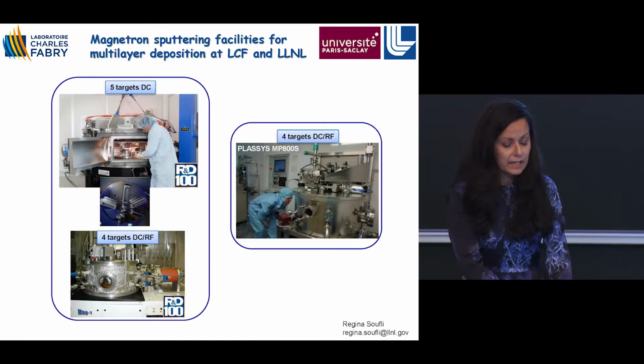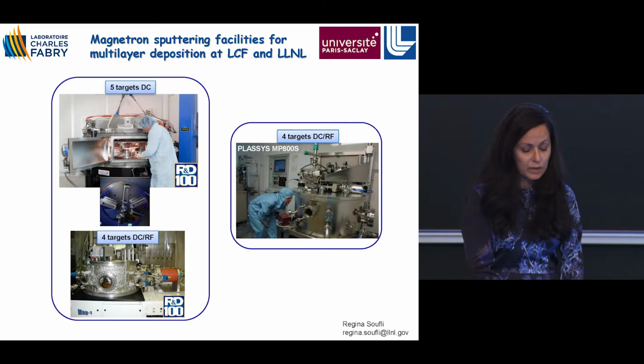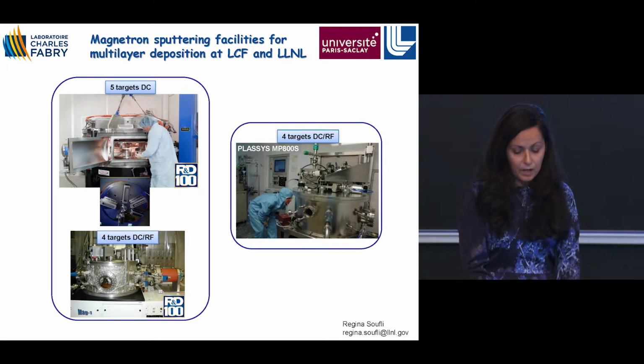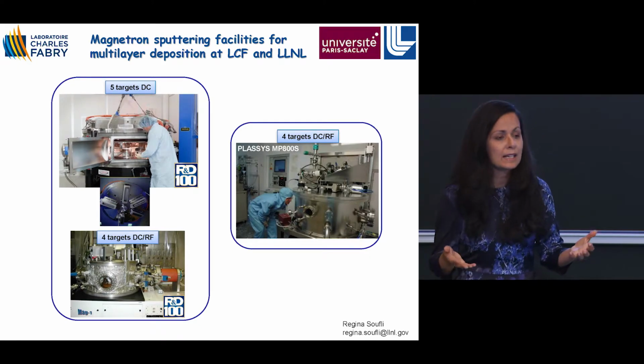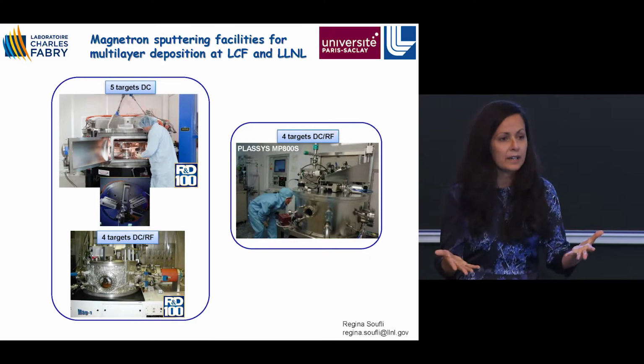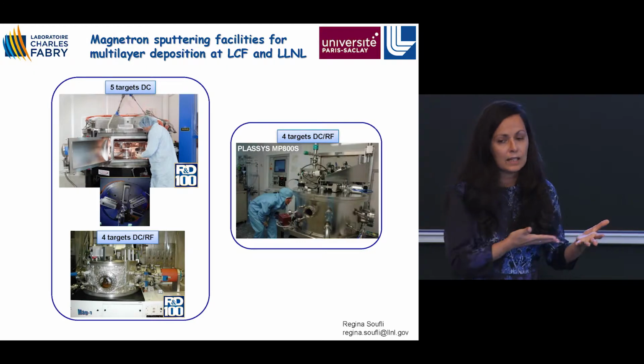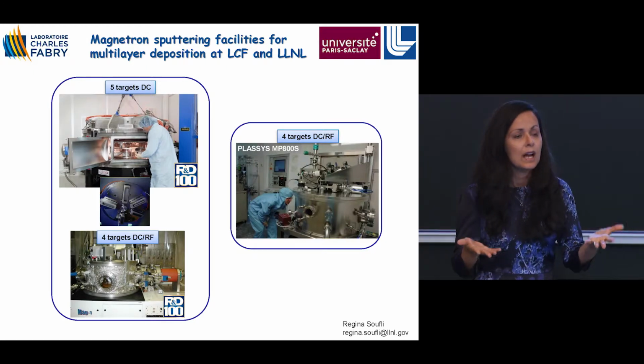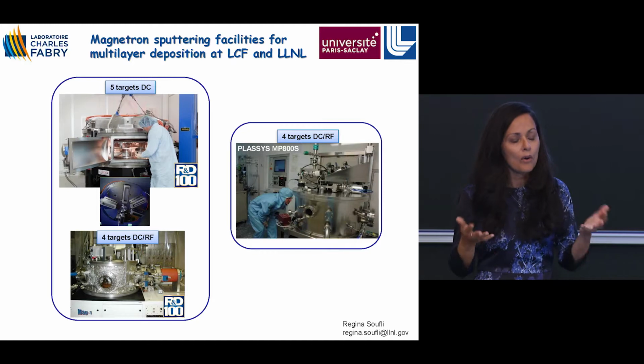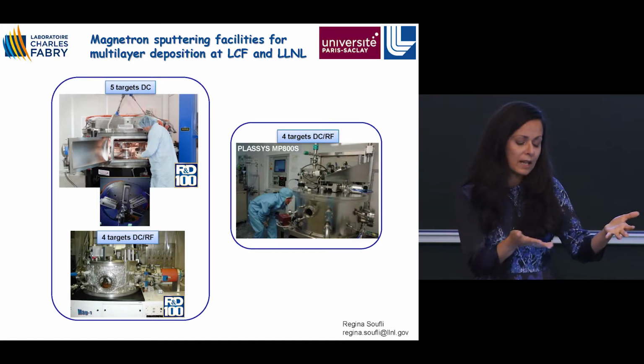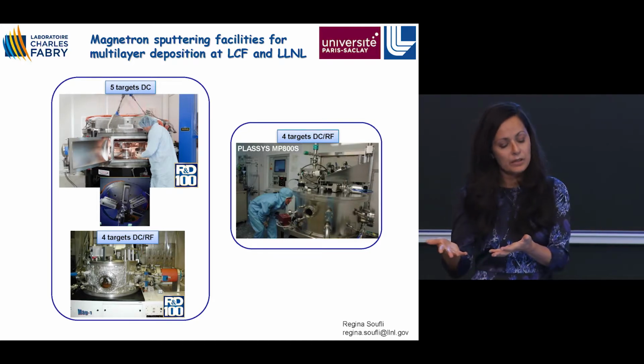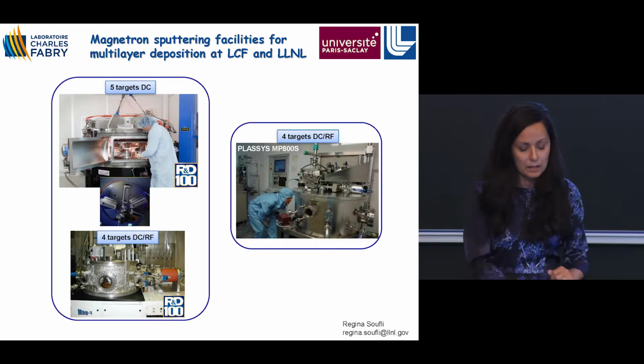Just to give you an idea, these are our deposition systems at Lawrence Livermore on the left and at LCF on the right. These are, again, vacuum systems, magnetron sputtering systems. They operate in a planar geometry. You basically have your substrate on a platter, which is rotating at about 1 RPM velocity underneath or on top of your sputtering target. So you pass under one material, then you pass under the next material, and this is how you make the multilayer.